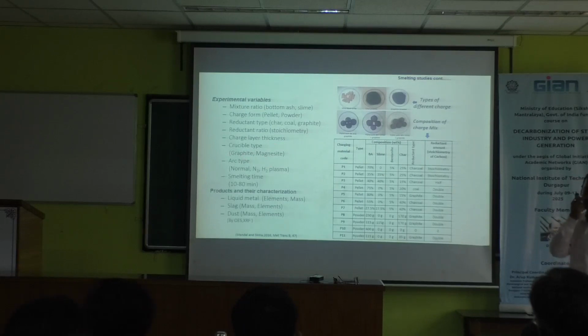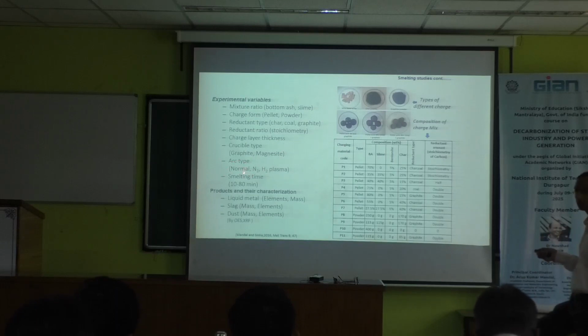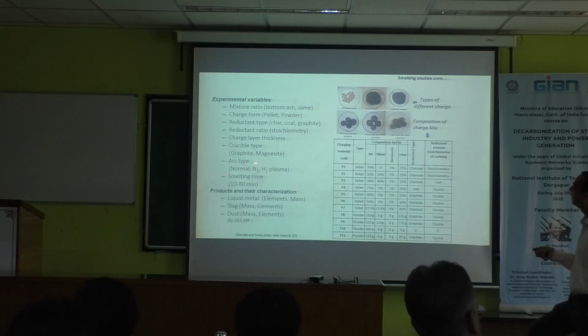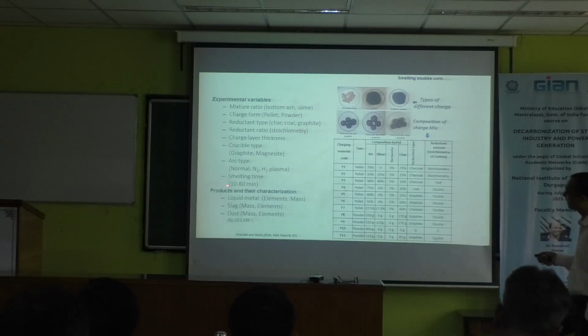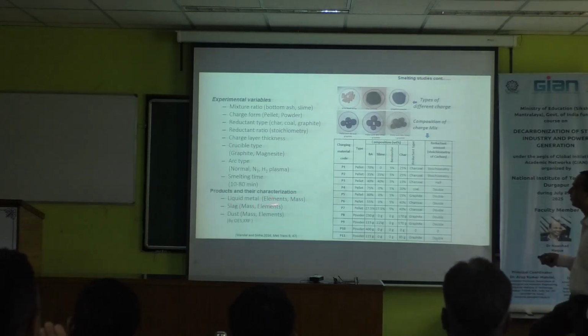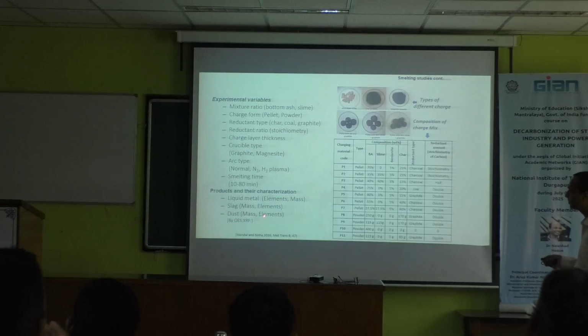We have changed the crucible lining materials like graphite, magnesite, and normal, with normal arcing, nitrogen plasma, as well as the hydrogen plasma. Smelting time we have varied from 10 to 80 minutes. Production was characterized for the liquid metals, like different elements and how much liquid metal is produced. Slag, how much slag is produced and its composition. Dust, how much dust is produced and its composition.